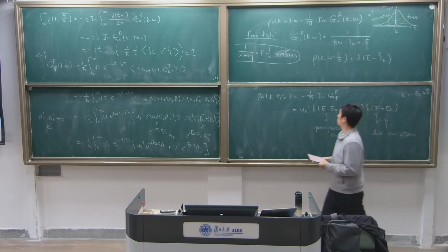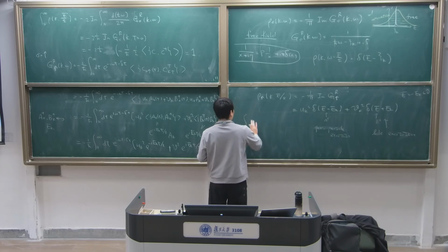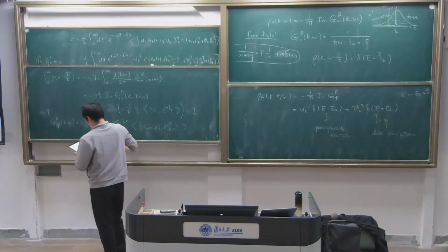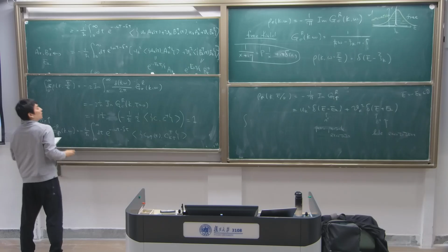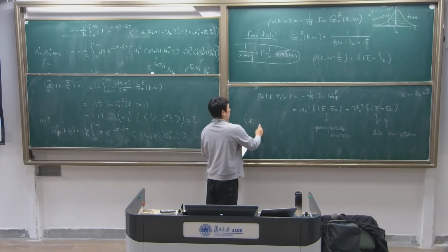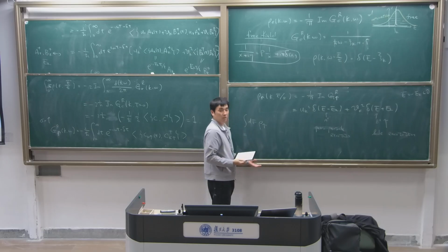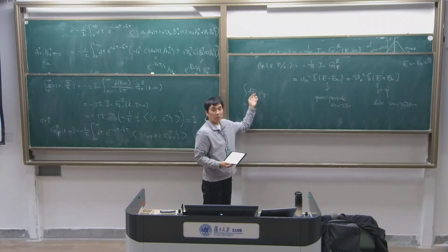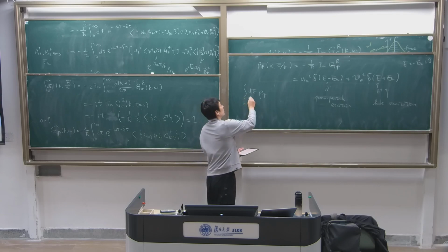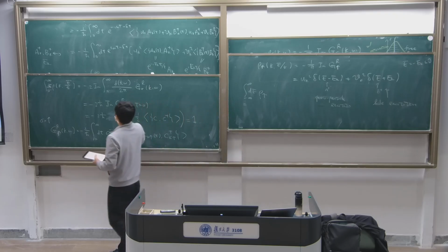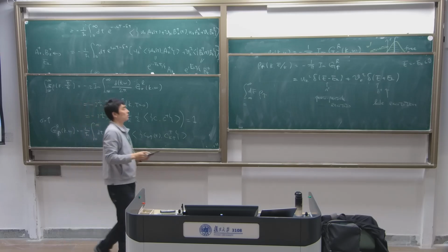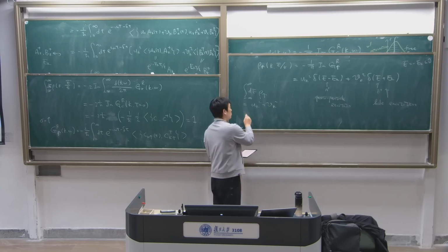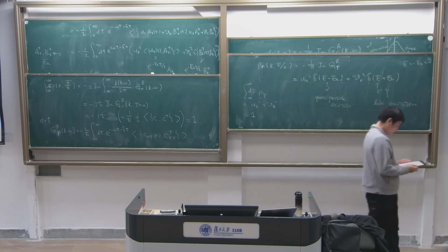And as you can see here, if you integrate over rho_k, as I mentioned, if you integrate dE, and you can easily see dE of rho, this is equal to what? Can you tell? If you think about integrating the spectral function dE, what do you get? Yeah, actually, this is u_k squared plus v_k squared. Alright? This is equal to one. Okay, so that's as we expected.